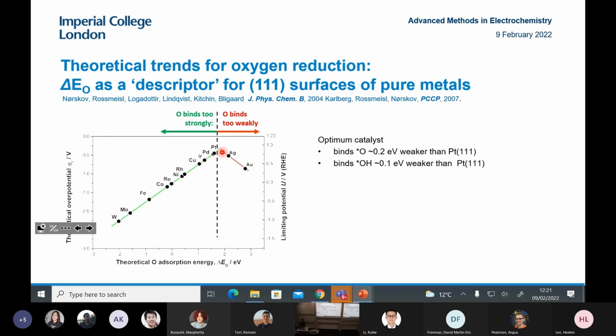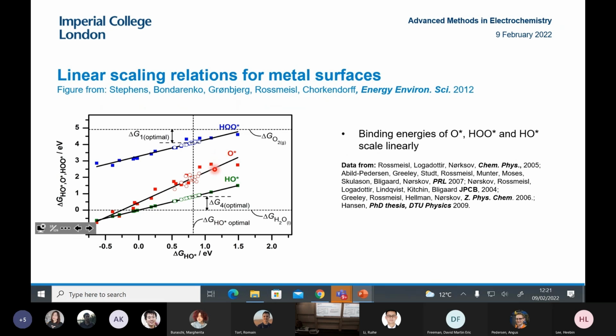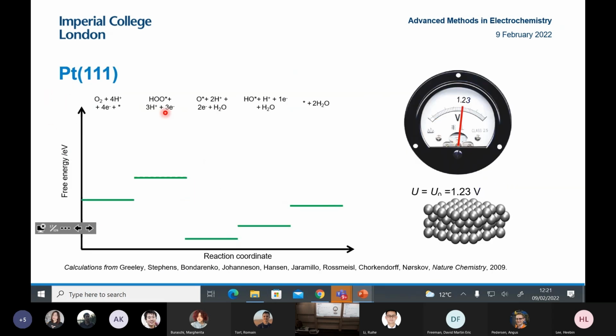So if you look at a surface like gold, typically the problem of gold is it binds oxygen and OH too weakly, and that it's limited by the activation of the oxygen. So it's more uphill to make OOH. Conversely, if you look at a catalyst like nickel, it binds oxygen too strongly, and then it'll get poisoned by the reaction intermediate. So platinum is actually at the peak of the volcano, or close to the peak, not quite at the peak, simply because you have a better balance between the first step, going from oxygen to OH, and the OH to water. They're approximately equal in magnitude. When they're actually equal is at the peak of the volcano.